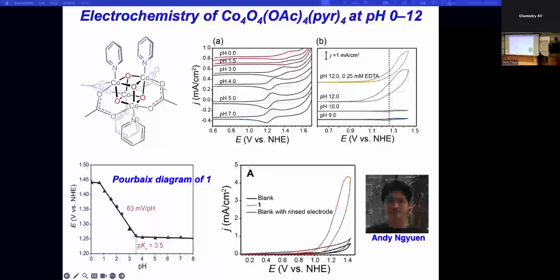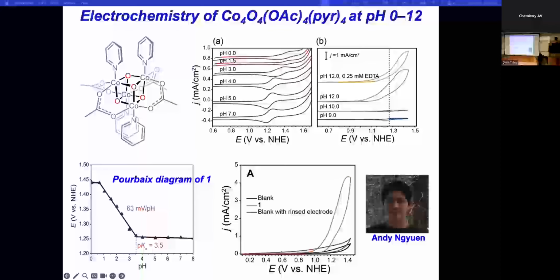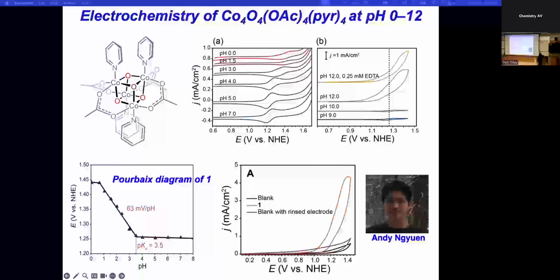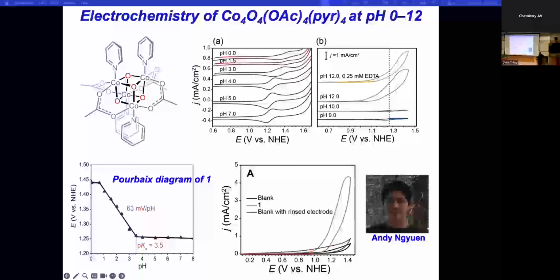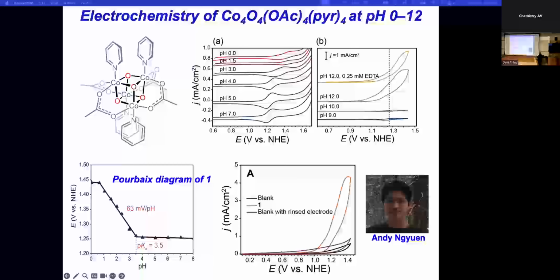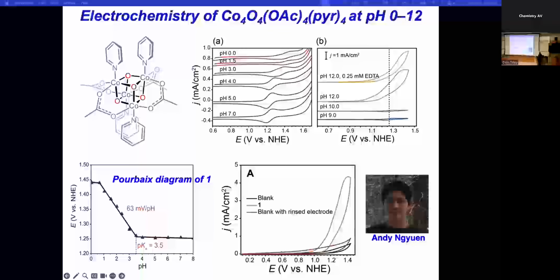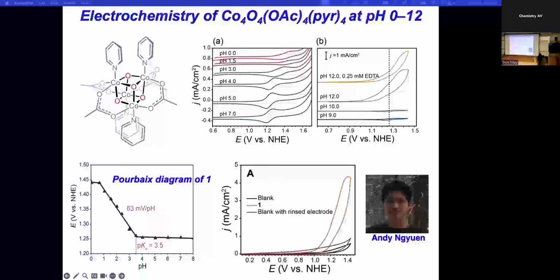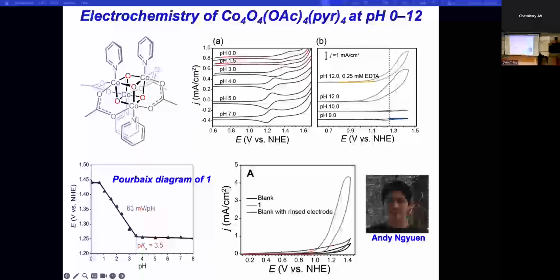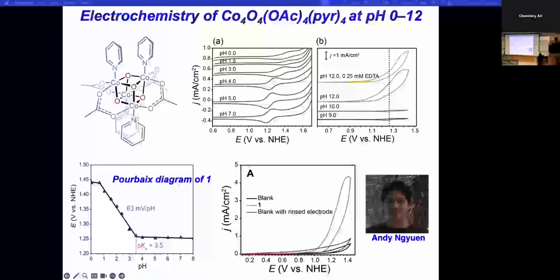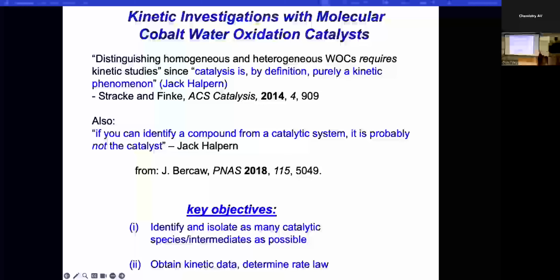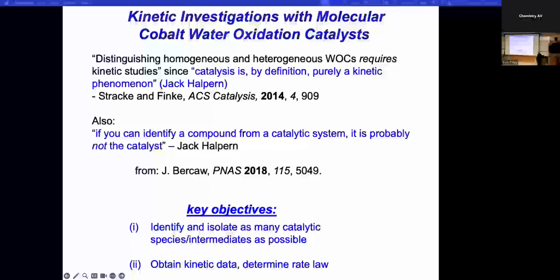The problem here in nailing down mechanisms in catalytic water oxidation is that if you're at a potential that's high enough to split water, you're at a potential to break almost any ligand you have and convert whatever species you add to cobalt oxide. In fact, almost every cobalt species that we had looked at up until this point, we could tell was decomposing to that layered cobalt oxyhydroxide, which is then a catalyst for water splitting. So is that a real catalyst? Well, we have to really do kinetics to figure out whether that species is the real catalyst or not.